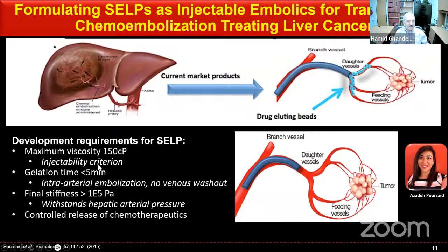That's the idea. So the design parameters that we needed were a viscosity not more than 150 centipoise, so we can easily inject these polymeric materials until they reach the tumor. We wanted a gelation time less than 5 minutes, so we wouldn't have any venous washout. We needed a stiffness of these polymers of 1 × 10⁵ Pascal, so it withstands the hepatic arterial pressure.